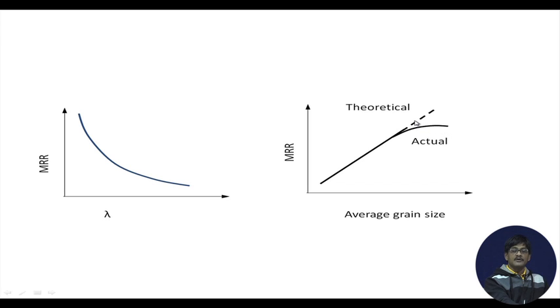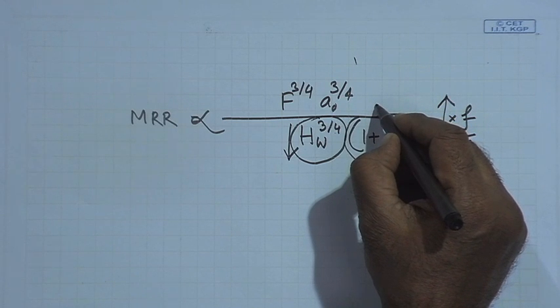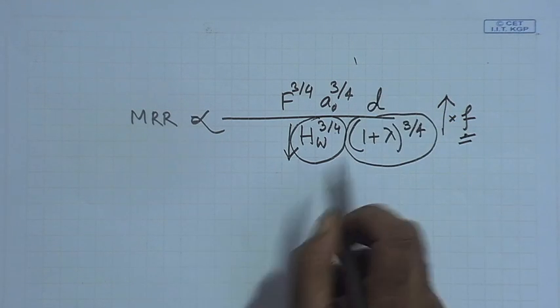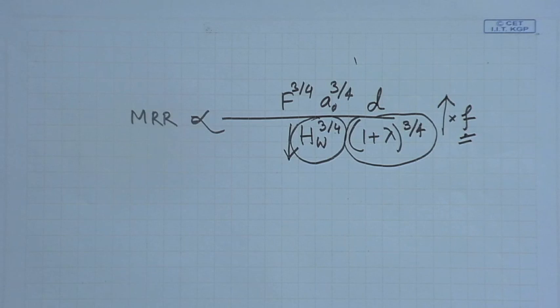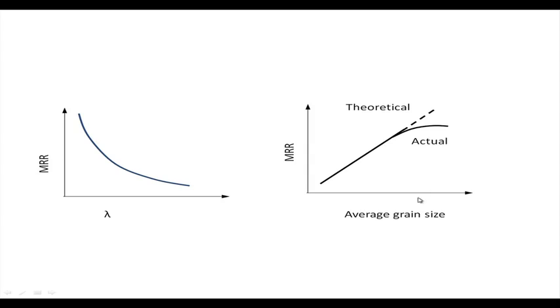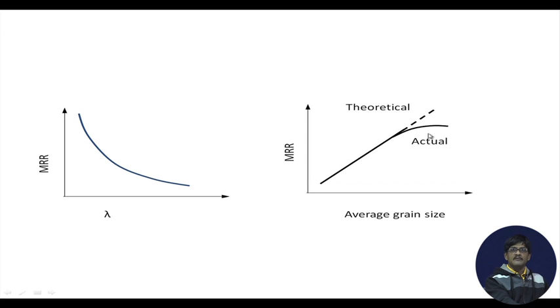Why should it go up? Because once again in this expression we have D here. So, it should be proportional, but instead of that it actually droops. Why? There are a number of reasons for this. One is crushing. When it is becoming more or less equal to the amplitude, it shows a crushing tendency, and also it finds difficulty to enter the gap between the tool and the workpiece, because it is large in size compared to the amplitude. Okay.